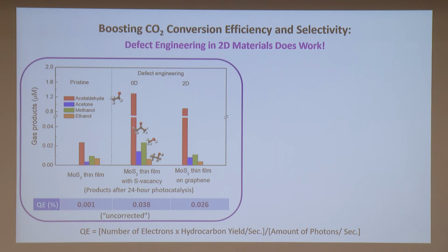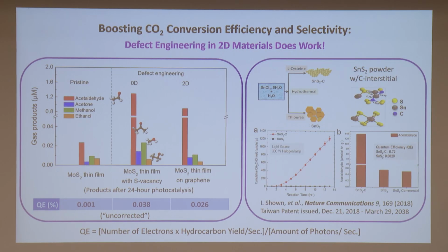So this is apparently an underestimated number, because we assume all the photons put in are absorbed. But nevertheless, for the powder, you can use a thick layer to maximize the light absorption. In this case, the apparent quantum efficiency for the tin disulfide with carbon interstitials introduced in the hydrothermal process, we can have also 2 orders of magnitude compared to the undoped. Okay, so this is reaching 0.7% efficiency. So this is still among the top efficiencies in our lab.